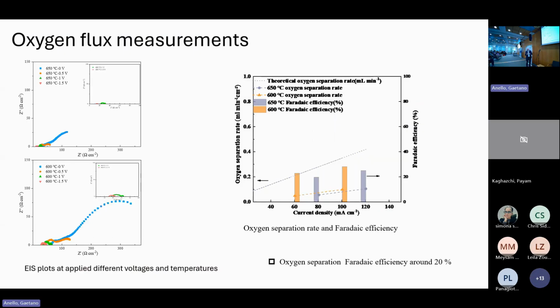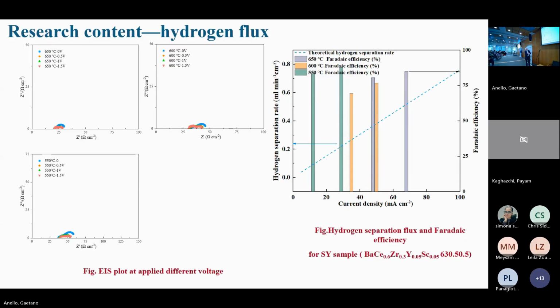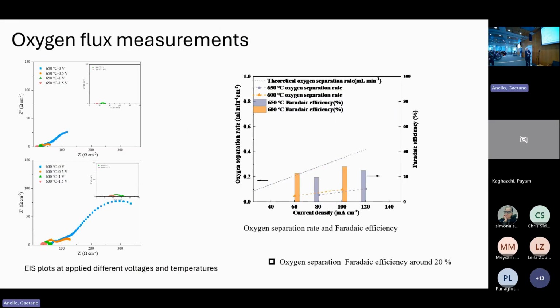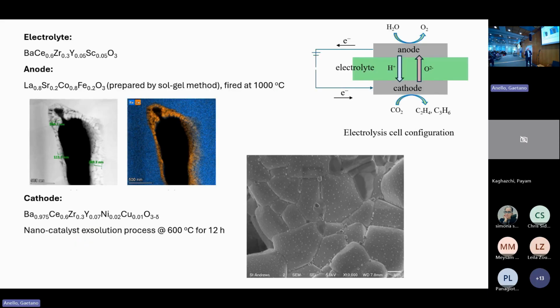And for oxygen, if you look at the electrochemical response, it's very simple. Electrodes work well. So the estimations of the transport number electrochemically are quite good that way. If you go to oxidizing conditions, the electrodes are less well behaved, so you have to be quite careful about the transport numbers. But measuring the gas that transmits, you can see again about 20% transport number of the best samples for oxygen. So we've got compositions that we can take forward, and that's going into the next stage of the project. So we've got an electrolyte.